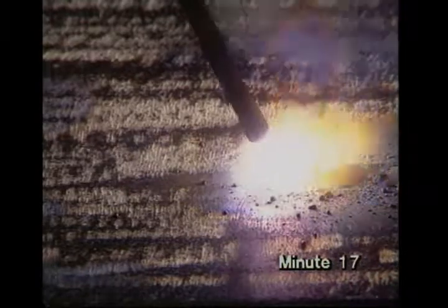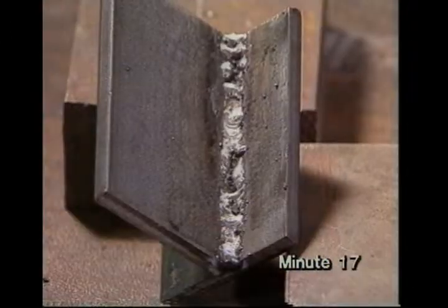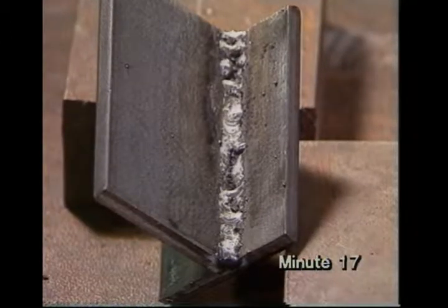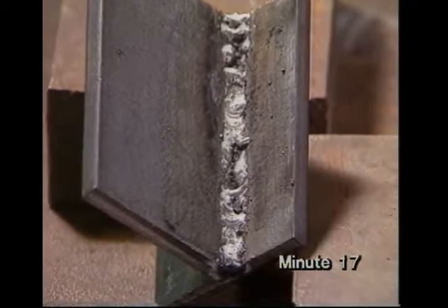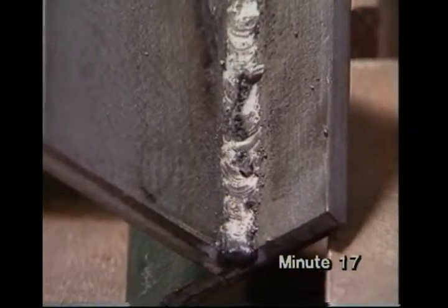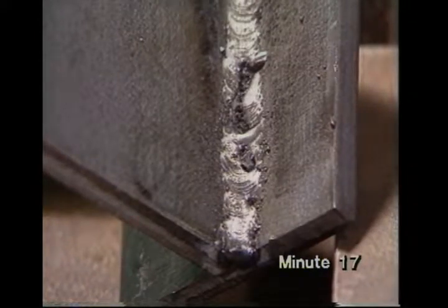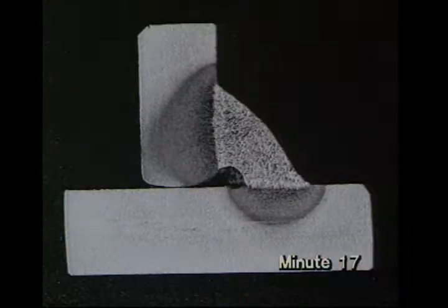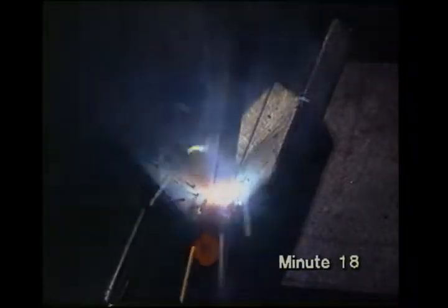If the arc is too long, when you weld a joint, it's even worse than welding on a flat plate. The weld metal has a rough surface and doesn't melt in properly. The slag is trapped inside the metal. The slag and poor melting show up in a macro section. The weld will be weak. If you move along the joint too slowly, then the weld metal piles up, trapping slag underneath.